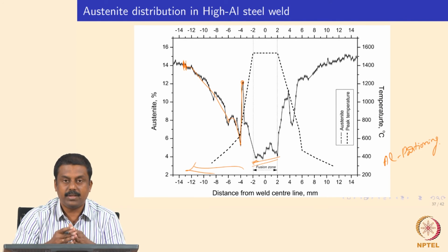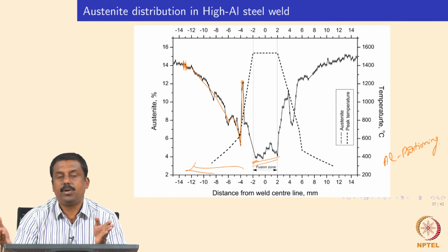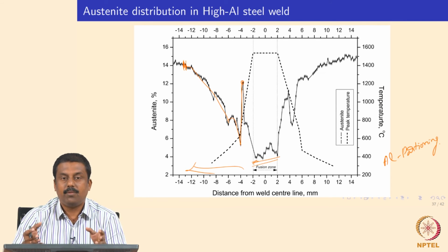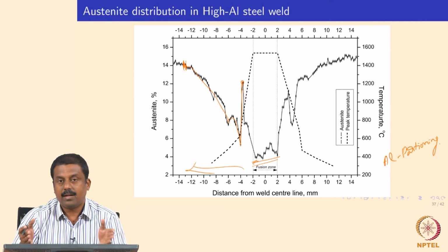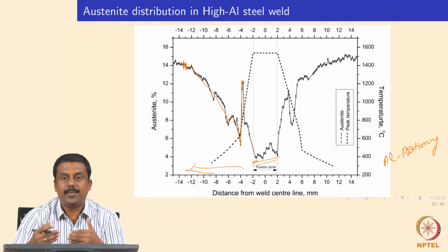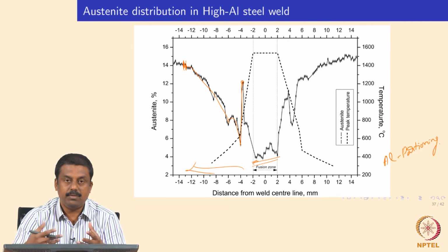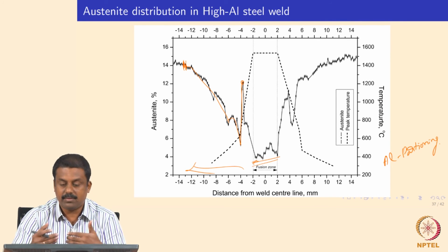And based on the peak temperatures, we can have varying amounts of retained austenite fraction. The other lesson I want to give you here is, if you have metastable phases like retained austenite in the microstructure, you will also enlarge the heat affected zone. Conventionally, in ferritic pearlitic steel you won't see any noticeable effect until your peak temperature reaches close to the A1 temperature, and you will see maybe some very small effect which is not noticeable in terms of the properties as well as the microstructure.